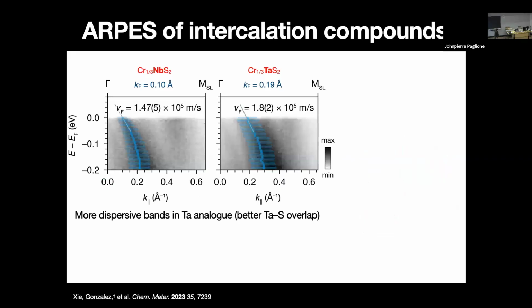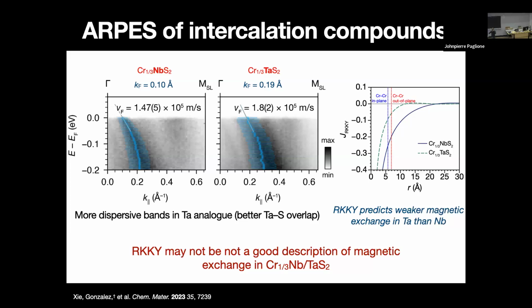Okay, and so what we can do then is look at the niobium and the tantalum analogs. We can measure their electronic band structures and extract some information about the Fermi wave vector. And what you find is that indeed, even in the intercalation compound, the tantalum analog is more dispersive. It has a larger hole pocket, and in fact, the magnitude of that Fermi wave vector is exactly opposite what you would expect, considering that the tantalum analog has a higher ordering temperature. If you model that RKKY interaction, you would actually predict that there should be weaker magnetic exchange in tantalum than in niobium, and that is opposite of what you observe, with the tantalum analog having the higher magnetic ordering temperature.